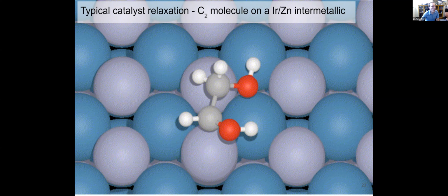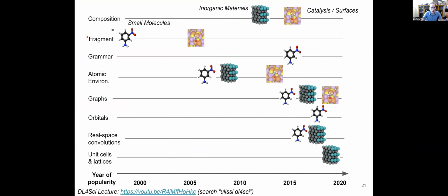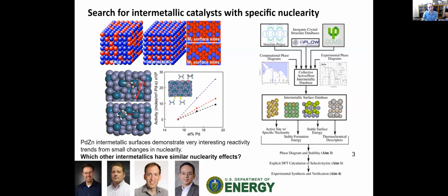Sure. Okay. So there's a question on alloy solid solutions. When are they going to do something different for CO2 reduction or HER compared to intermetallics? So that's a great question. Basically, it comes down to whether or not you get very specific behavior for specific ensembles. If you just sort of have an averaged effect, maybe it doesn't matter, and maybe it's very similar. But if your adsorption location really requires two metal active atoms to be right next to each other, and if they're isolated, that might do a different chemistry, this is a specific situation where you might get different behavior. It doesn't happen all the time. In this case, it happens because the adsorbate's a little bit larger, but it does happen sometimes. So there's not one clean answer to that.